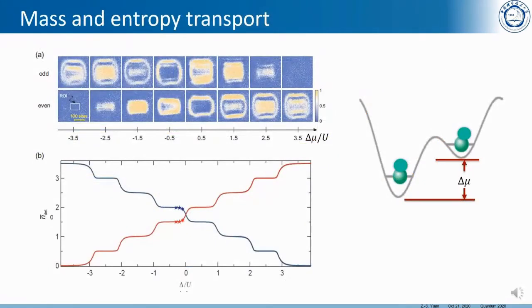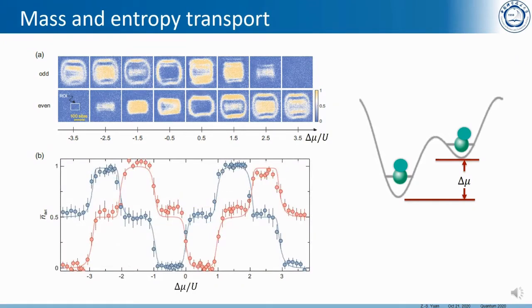For different tilts of the superlattice, we studied the atom redistribution in the samples and reservoirs by Monte Carlo simulation. The curves here have a few steps, which indicates the gap protection from excitations. The experimental result confirms the steps as well, and the sharpness of the edges is used to calibrate the temperature and entropy.